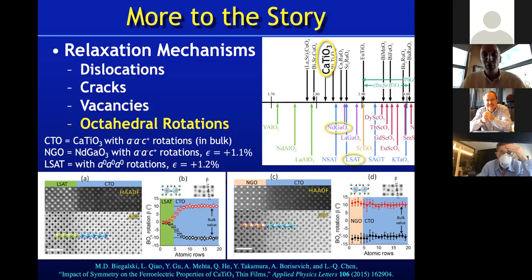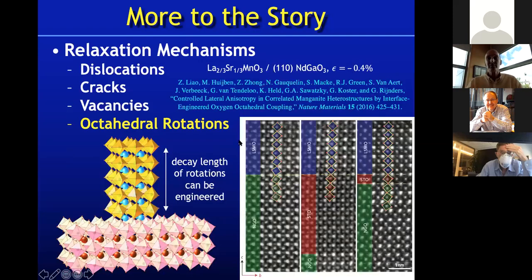So here I'm showing you that this is a richer scenario than simply, immediately having this strain. Even in a fully commensurate film, there is this regime in which you can have these octahedral rotations evolving from the interface into the film. And the length scale over which those octahedral rotations evolve can vary depending upon what materials we're talking about, as well as even what intermediate materials there are.